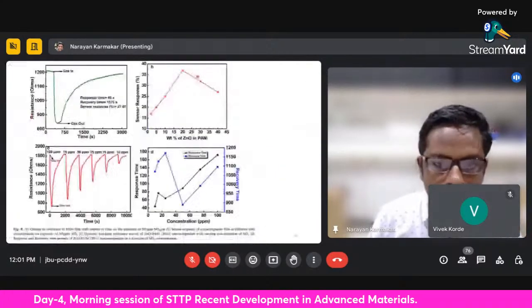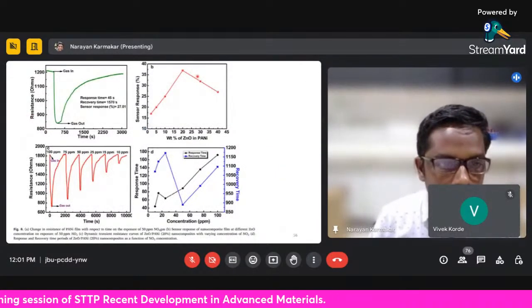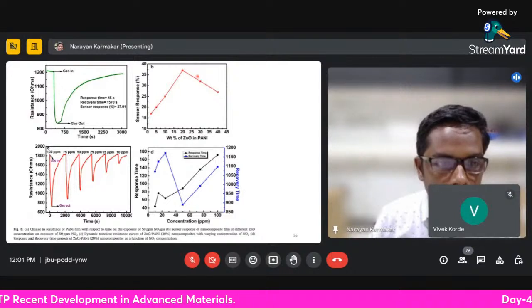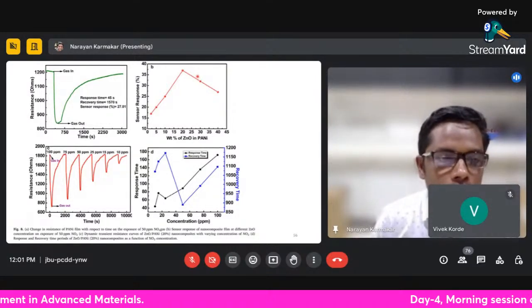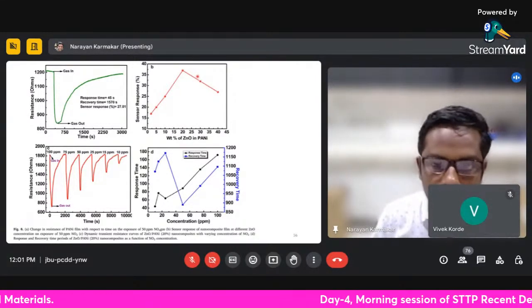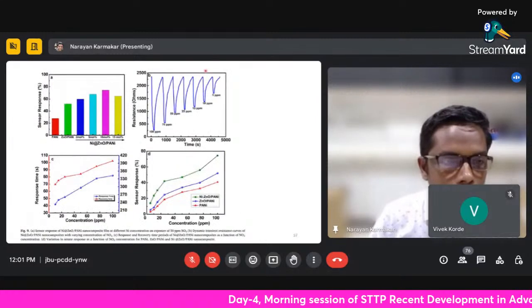So what we did is this: after optimizing the zinc oxide nanoparticle concentration in the PANI composite, we then doped it with nickel.